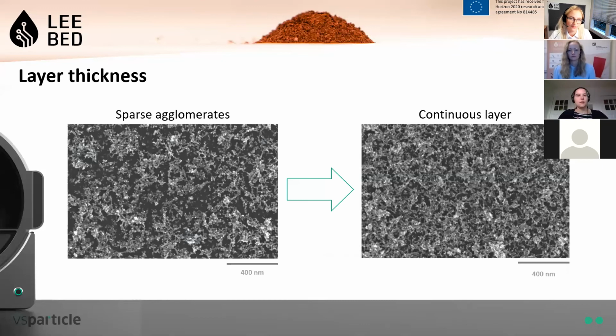On the next slide, I want to show you examples of various layer thicknesses. On the left, you see a submonolayer. You can clearly identify the sparse agglomerates that are scattered over the silicon substrate. And on the right-hand side, it's a thicker, continuous layer. So typically, we can print layers of a few micron thicknesses within a reasonable print time.